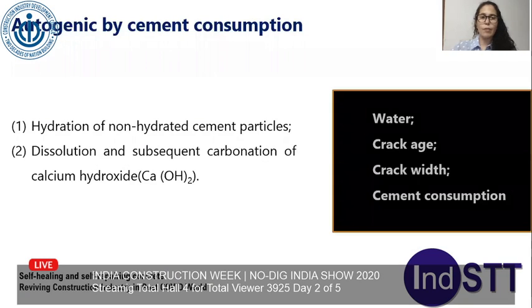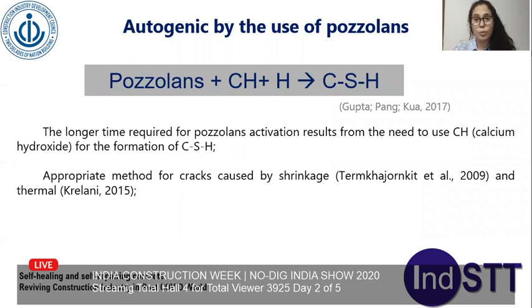For self-healing mechanisms, we have autogenic by cement consumption. We have two options: hydration of non-hydrated cement particles, and dissolution and carbonation of calcium hydroxide. This mechanism is influenced by water, the crack age, the crack width, and cement consumption. We have also the autogenic by the use of pozzolans. They react with calcium hydroxide and water, and they promote the CSH. This is related to cracking at early ages, when we still have pozzolanic reactions occurring.